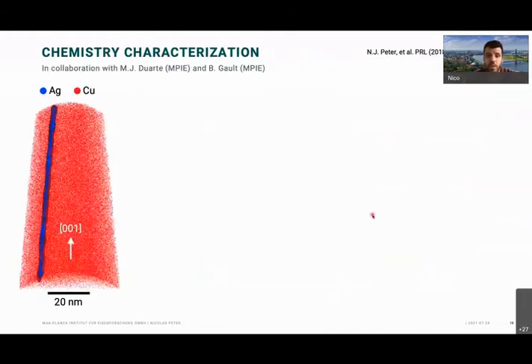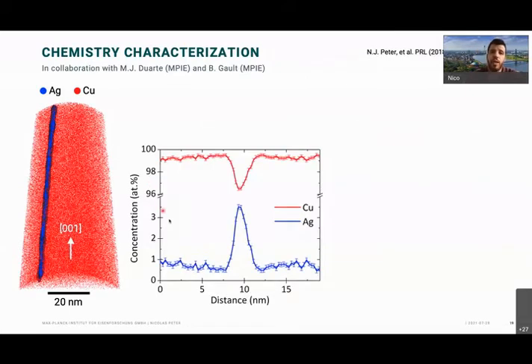To confirm that this is actually silver at the boundary and not just saying this is bright and not so bright columns, we did atom probe tomography, and we can see here, well, we do have certainly silver segregated to the boundary and mostly to the boundary, how it's supposed to be after the faceting, the phase diagram of copper silver. We can also see this in the concentration profile, that at the boundary we get about 3 to 4%